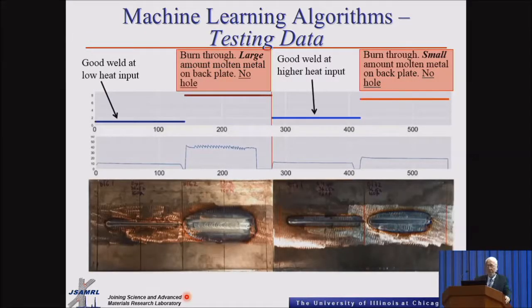So we proceeded with the testing of the machine learning algorithms. You can see for the good weld, in this case we know that we had a good weld, and what was the prediction? For this input, it indicated that you have a good weld.